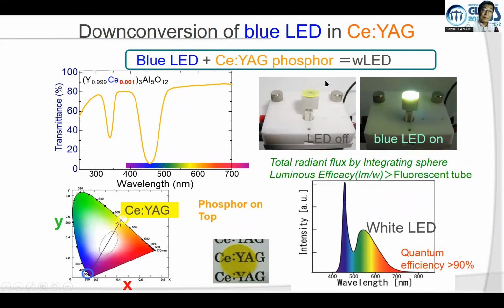And YAG can be made into transparent ceramics. And it's good to compare the transmission spectrum instead of reflectance spectrum. This is the in-line transmission spectrum. You can see 460 is a peak, 340 is the second 5d excited state. And color coordinate can be tuned between the blue point of LED and that of YAG-cerium, the yellow point, having this broad emission. So depending on the thickness of the ceramic phosphor, we can choose the color coordinate between this region, bluish white to yellowish white.